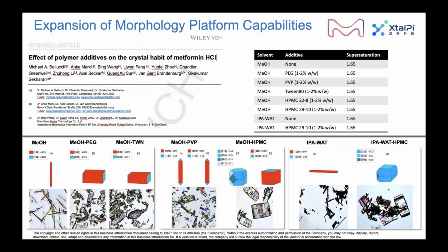And it has some interesting properties in terms of the effect of additives on its morphology. So in pure solvents, metformin HCl yields needle-like crystals, but it's been observed that polymer additives and some other additives can yield much more desirable morphologies. So when we were discussing a potential morphology project, this particular system came up, and the challenge posed to us was basically, are the simulations able to capture this effect that the additives have on metformin HCl?